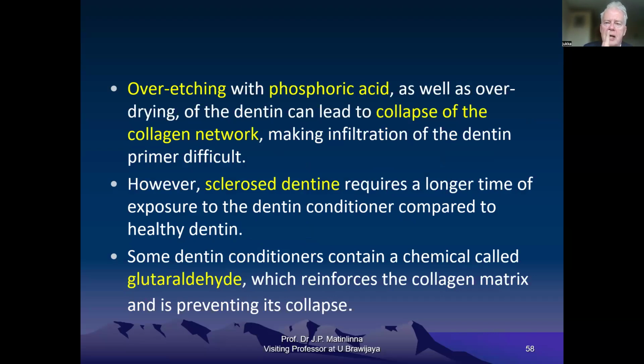Over-etching with phosphoric acid as well as over-drying of the dentin may lead to collapse of the collagen network, making infiltration of the dentin primer difficult. However, sclerotic dentin requires a longer time of exposure to the dentin conditioner compared to healthy dentin. This is also important to bear in mind. Some dentin conditioners contain a chemical called glutaraldehyde, which reinforces the collagen matrix and prevents its collapse.